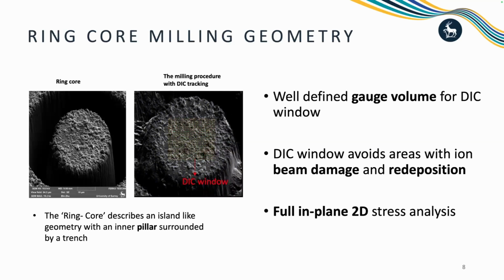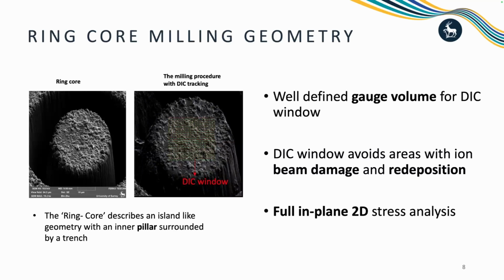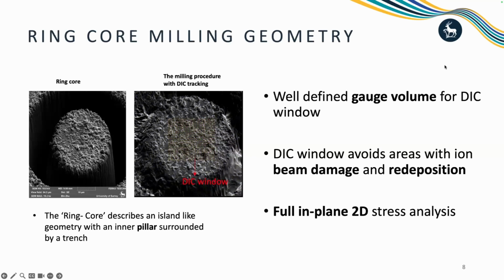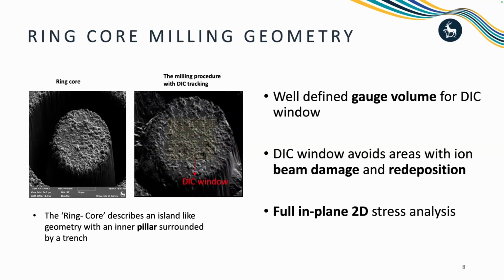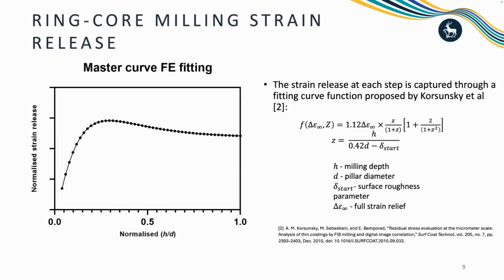Here are the experiment procedures. We do the incremental milling, take the SEM image, and use DIC to mark this region and analyze the deformation of this region during the stress release. And after the calculation at each incremental milling, we fit the stress release value at each incremental point, and finally use this master curve to get the residual stress results, the residual strain release results.